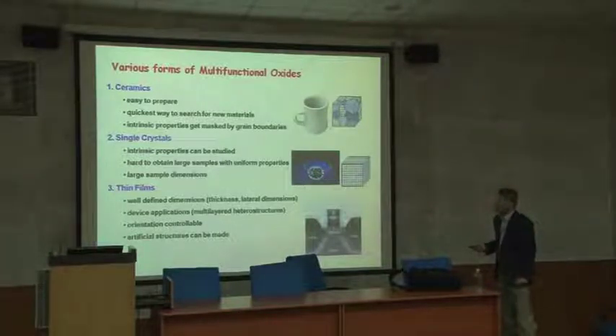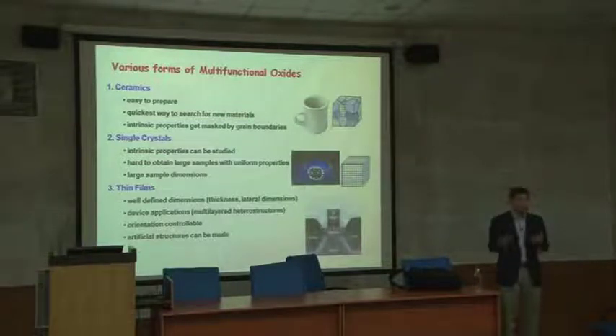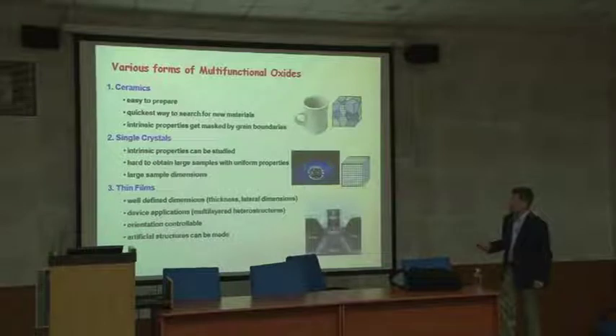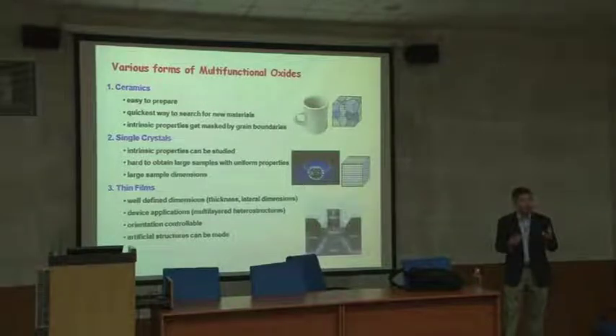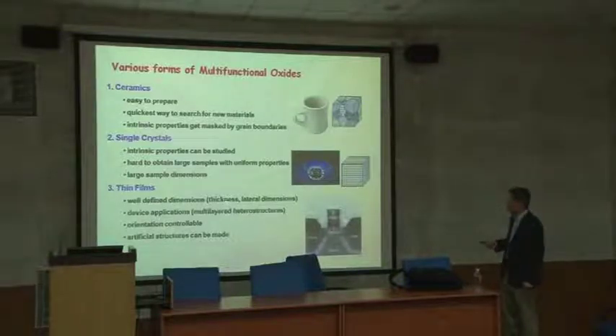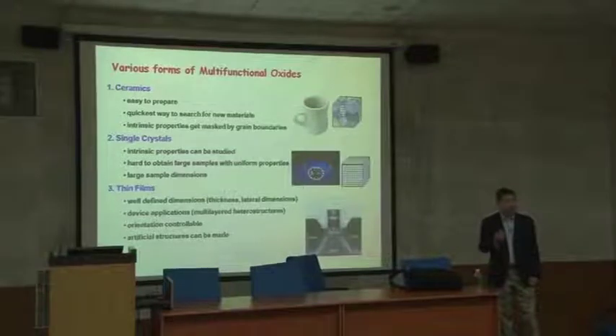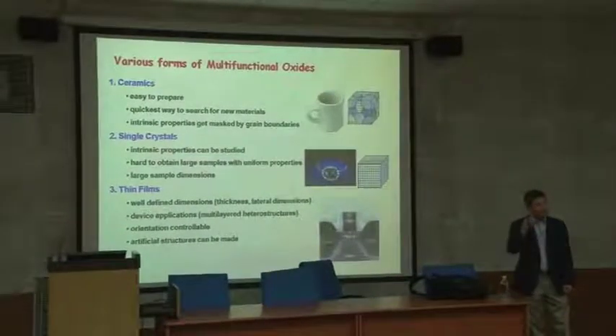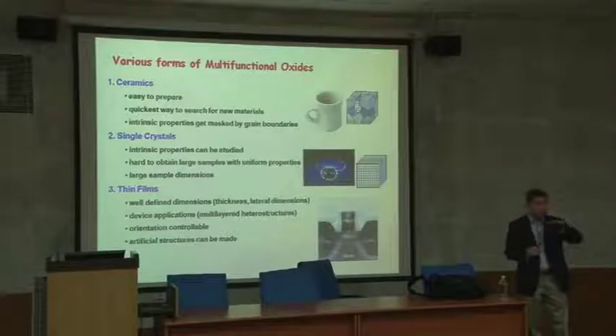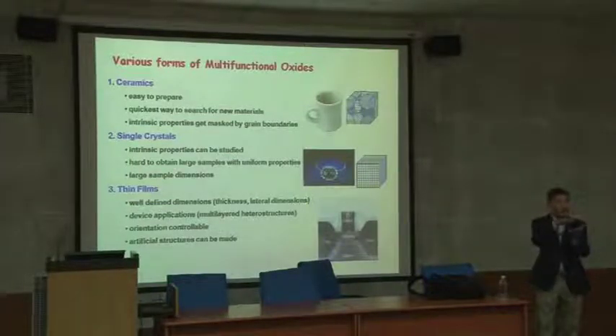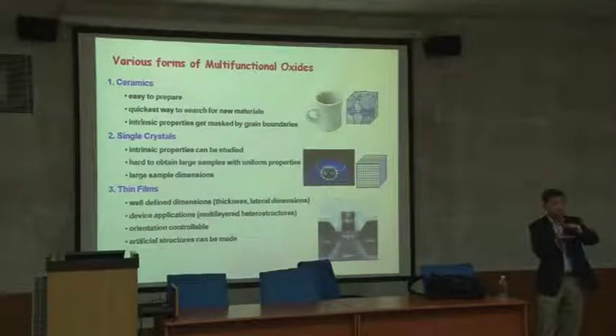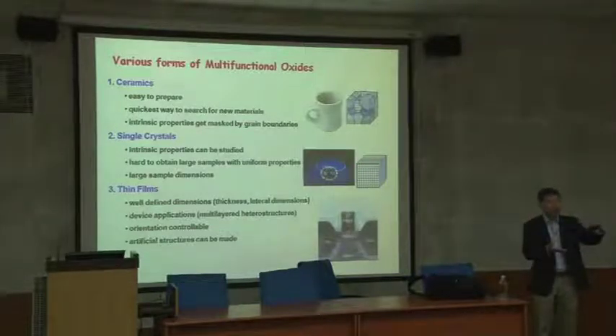The material form I'm going to talk about in this lecture, in most of the lectures I'm going to cover, is thin films. And this is a very exciting material form, and there are many, many reasons we study thin films. With thin films, you can make the dimensions very, very small, and even the thickness dimension can be one monolayer. Okay, atomic one monolayer is not necessarily one unit cell. One unit cell formation is basically binding two layers, as I showed in the strontium titanate crystal structure: strontium oxide and TiO2, two layers form one unit cell.